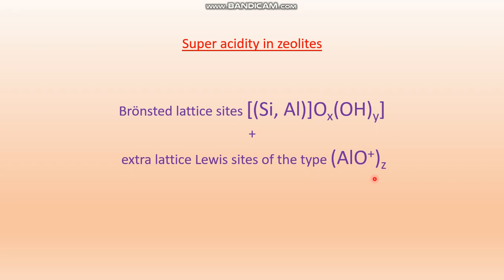These species may be formed locally upon steaming of H zeolites, and it is therefore logical that the presence of such sites, if they exist, reflects the type of thermal treatment the sample has undergone rather than its chemical composition. Neither the activity in reactions requiring this type of site can be explained nor predicted in terms of overall chemical composition.